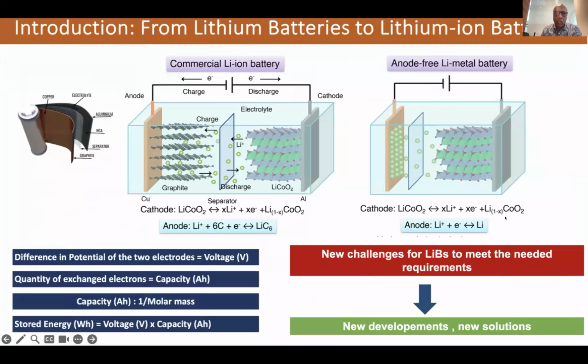So briefly, a lithium-ion battery is not a lithium battery. We started first with the lithium battery, using lithium metal, okay? Lithium metal, and we have a cathode material on the cathode side. But unfortunately, during charge and discharge of a battery using lithium metal, we have this phenomenon that we call lithium growth. So lithium metal, which is metallic and a conductor, starts to develop what we call dendrites. And during cycling, we have short circuits between the lithium metal and the cathode material that can cause some safety issues. That's why Sony in 1991 had this big challenge to replace lithium on the anode side with graphite.